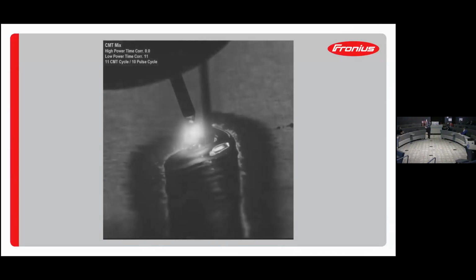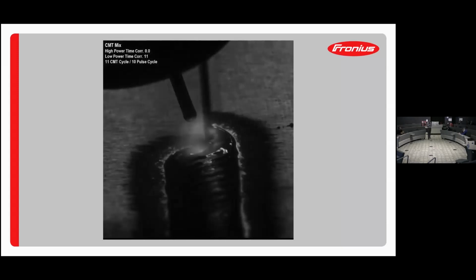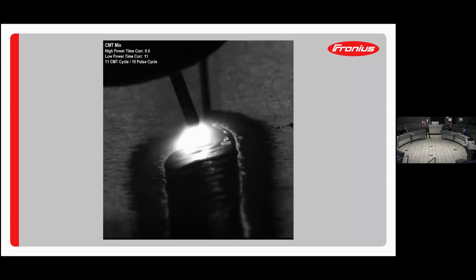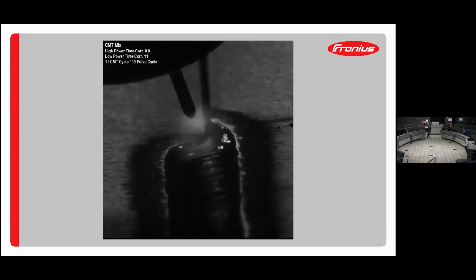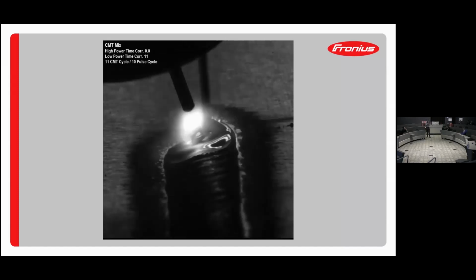On this next slide, we have an example of what's called the CMT Mix process. So rather than going through all three, this is standard. What's happening there is standard pulse welding. So you're getting a pulse of current. With each pulse of current, you get a droplet. Now it's doing the CMT. So you can see the wire going backwards and forwards, and the arc is created as the wire travels backwards. So the heat input with CMT is considerably lower than the pulse process. And that's an advantage when you come to additive manufacturing, because one of the problems that you have is too much heat. So by using CMT, you can minimize the heat into the process.